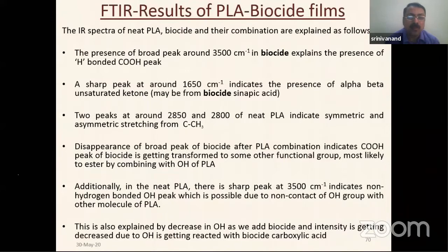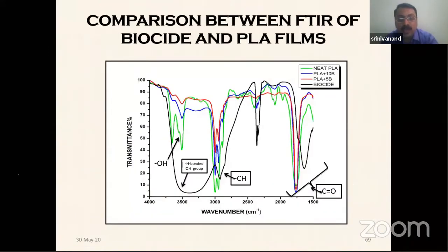The presence of a broad peak, as I told you, around 3,500 corresponds to biocide. A sharp peak around 1,650 indicates the presence of alpha beta unsaturated ketone present in biocide. And two peaks around 2,850 and 2,800 from neat PLA indicate the symmetric and asymmetric stretching of CH3. The disappearance of the broad peak of biocide after PLA combination indicates the phenolic acid is having an interaction with the PLA. So this is also explained by the decrease in OH as we add biocide, and the intensity is getting decreased. As you can see, the OH peak intensity is getting decreased as it is getting interacted with the PLA.